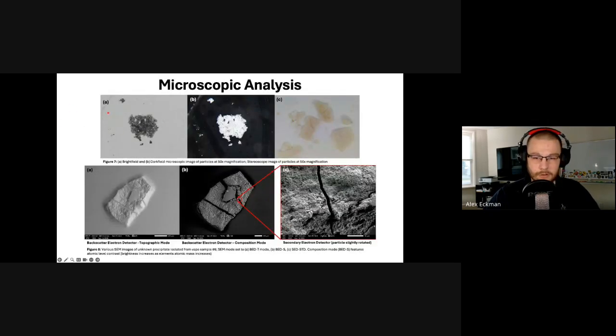We went ahead and got some microscopic photos of it, threw it under the stereoscope and various bright field, dark field microscopes, just to kind of really take a look at what we had. Now, it didn't really provide much definitive evidence at all. So we took a look under the scanning electron microscope, which we can see are these photos at the bottom. The interesting thing that we really saw here, if anything, was this bright white speck on the backscatter in composition mode. And that's really because the SEM has atomic level contrast brightness, meaning that different elemental weights are going to show up as a different brightness. And when we ran a particle analysis on that white speck there, it was actually an aluminum particle that was caught in the pellet. And so really not getting too much data from these other than some pretty SEM photos.